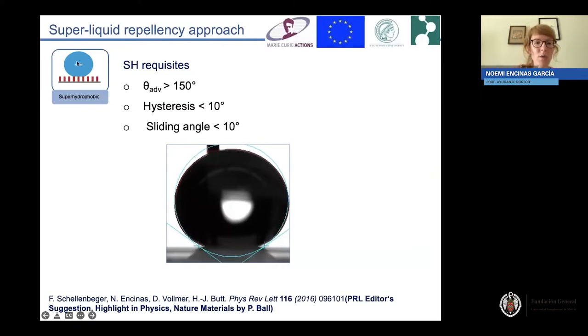So going to this very first superhydrophobic approach, we need to know that traditionally the conditions to define a superhydrophobic surface have been having an advancing contact angle of 150 degrees or above, defining this advancing contact angle as the one that we have on the front side of the droplet, of the liquid droplet, when the surface is tilting. A hysteresis below 10 degrees, let's say when this droplet is moving along a tilting surface, the difference between the advancing and the receding part, and also a sliding angle below 10 degrees.